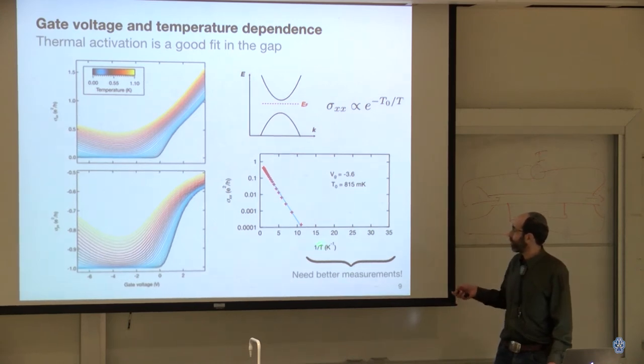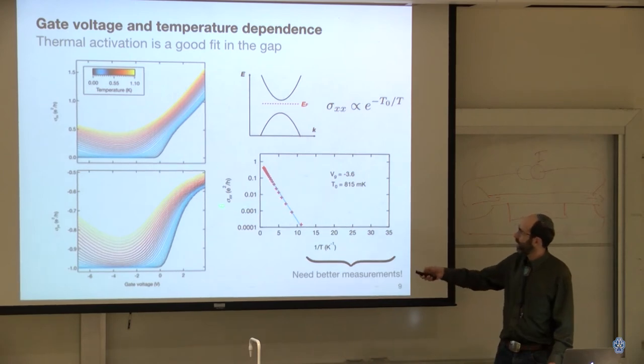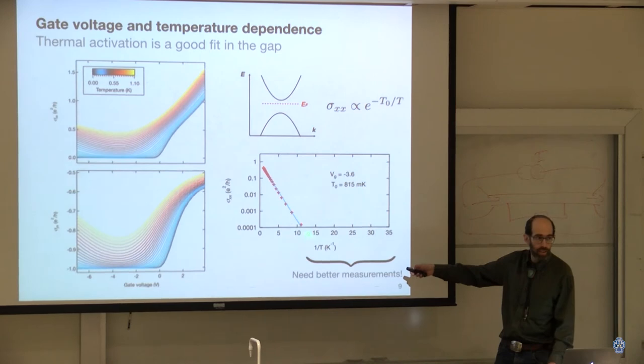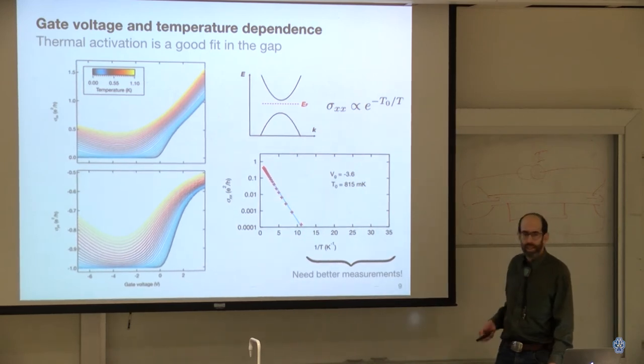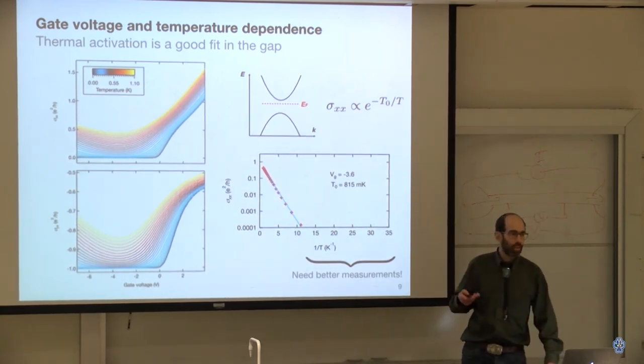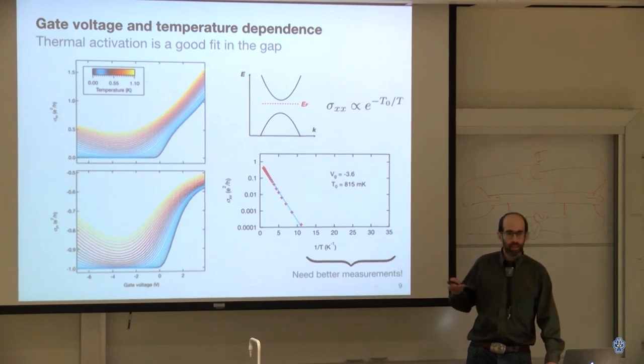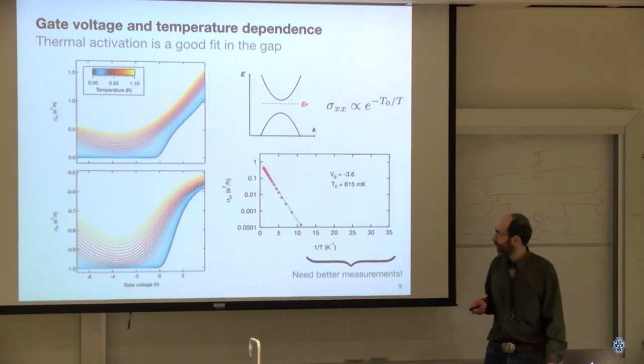Most recently, my group made better measurements. This is looking at the conductivity as a function of 1/temperature. It's on a log scale for the conductivity, and you see it's dropping off exponentially as you go down in temperature. That's what's called an Arrhenius behavior, or activated behavior. It's showing that temperature is what's jiggling things.